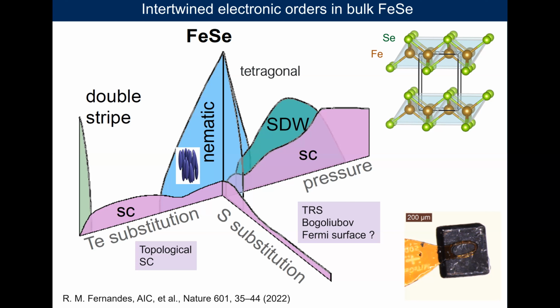So I'm not going to talk too much about this phase because this is some research we're doing right now. From the phase diagram itself, what's interesting is that both the superconducting and the SDW phases seem to follow each other initially, which is a bit unusual. So some μSR data predicted that you might have coexistence between the two phases, at least in this regime.